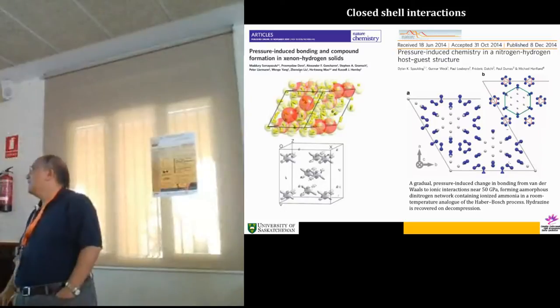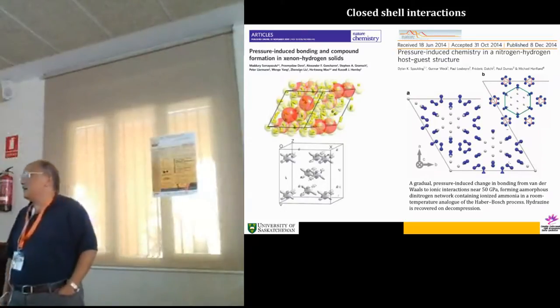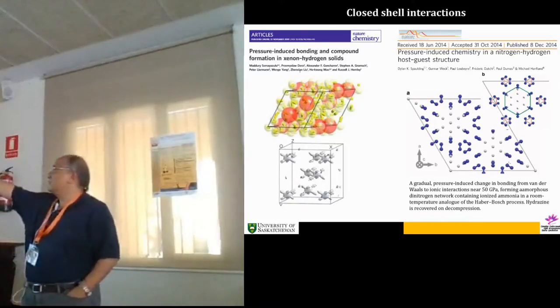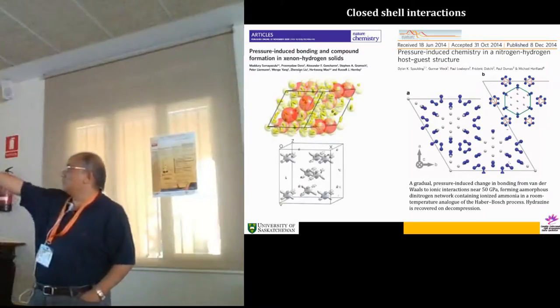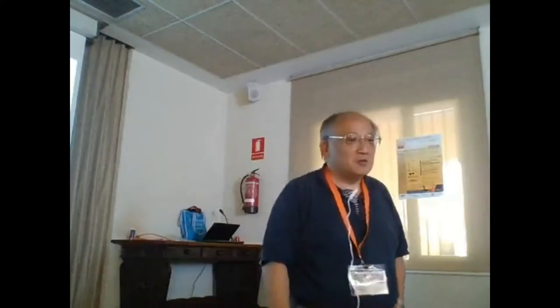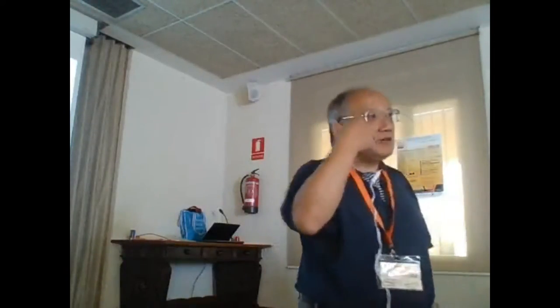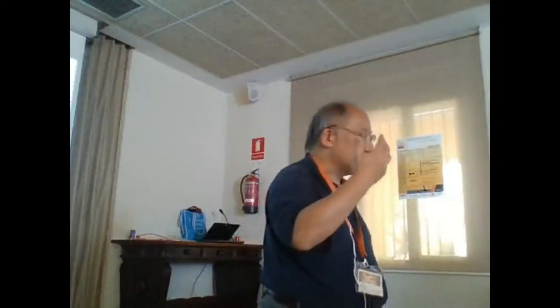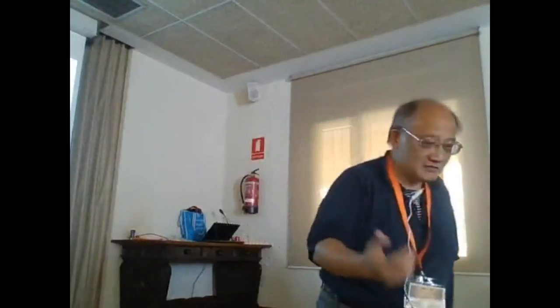Paul Loubeyre did it with nitrogen and hydrogen. It formed a clathrate compound. You know, the nitrogen forms a hexagonal ring and the hydrogen in between is trapped. So, very interesting. Though it occurs at a very low pressure to me, less than 50 GPa. It's all low pressure. I think most of us can safely do it without breaking the diamond cell, right? Well, if we go over 100, you need a steady hand.